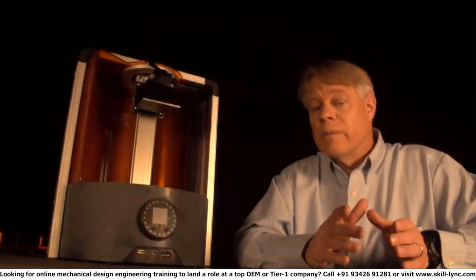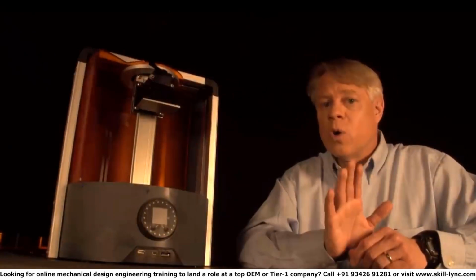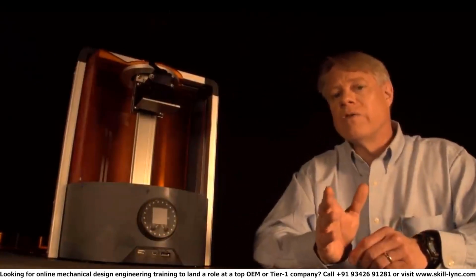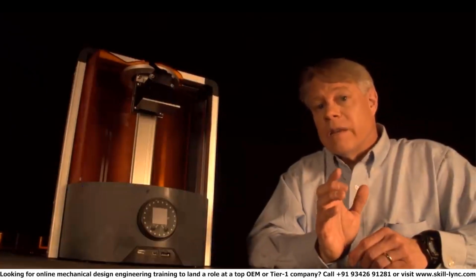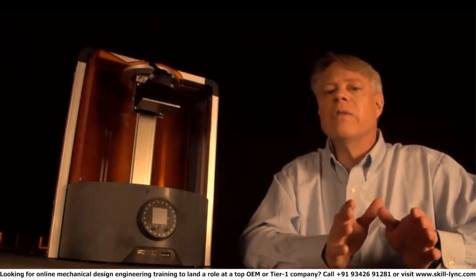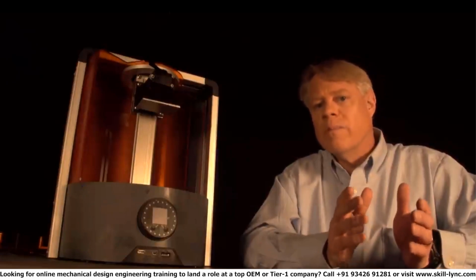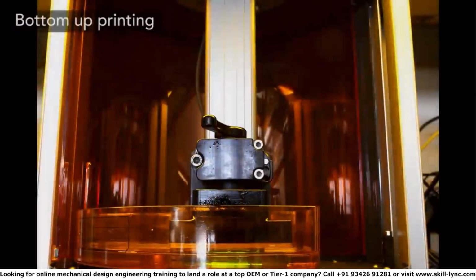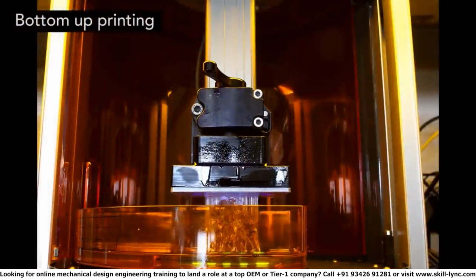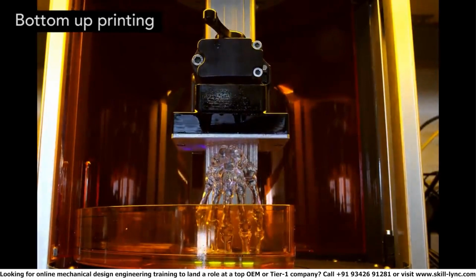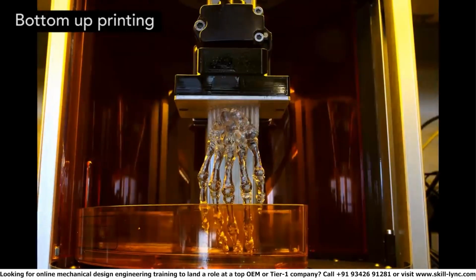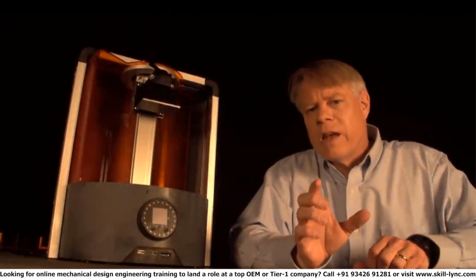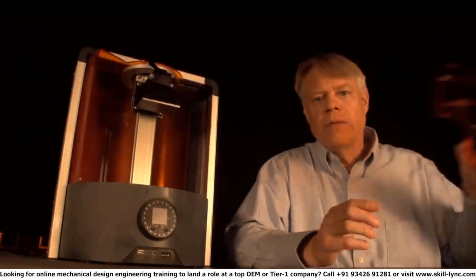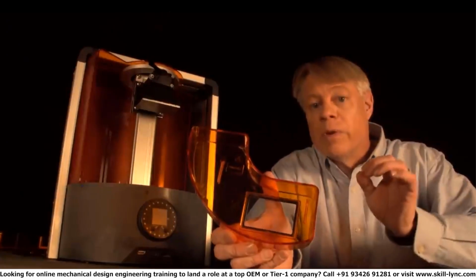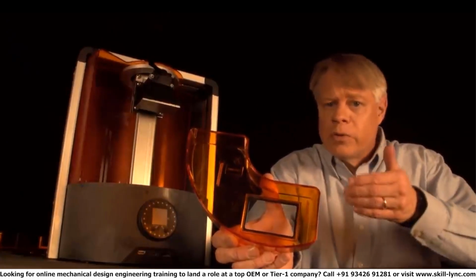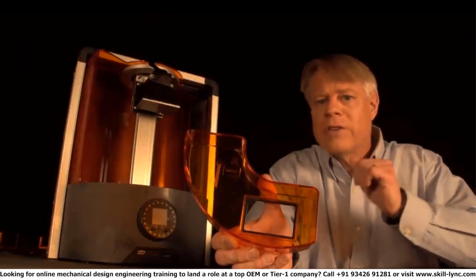But as you can see, this is an end model, and the surface of the model is very smooth. The resolution produced via stereolithography is very good, much better than FDM, right? You get no stair stepping, you don't get a rough surface finish. And also, because these layers are chemically hardened using UV lasers, the bonds in between layers are also much stronger. So these parts can be stronger in the build direction than through fused deposition modeling.